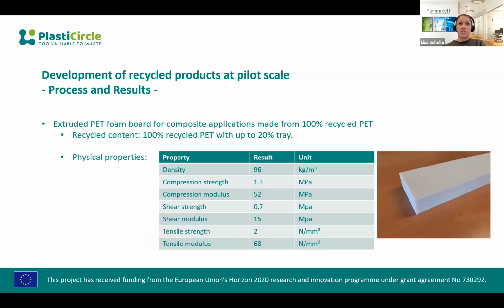Finally, we could prove that on pilot scale, with a combination of adapted processing parameters as well as newly developed melt modifier formulations, it's possible to produce foam boards from PET from trays that have a comparable quality to foam boards produced from PET from bottles. You can see here the individual test results from the demonstrator foam board that was produced in the course of the PlastiCircle project with up to 20% tray.